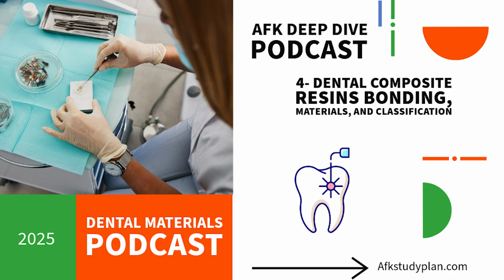And there's a lot of filler in there, right? Like 50 to 80% by weight. Easily. Sometimes 30 to 70% by volume, which is a huge proportion. These fillers are critical. Why? What do they actually do? Several really important things. First, reinforcement. They make the composite much stronger, stiffer, tougher, able to withstand chewing forces. Okay, strength. What else? They significantly reduce that polymerization shrinkage we just talked about. The fillers themselves don't shrink, so the more filler you have, the less overall shrinkage of the composite. Ah, that's clever. They also reduce thermal expansion and contraction.